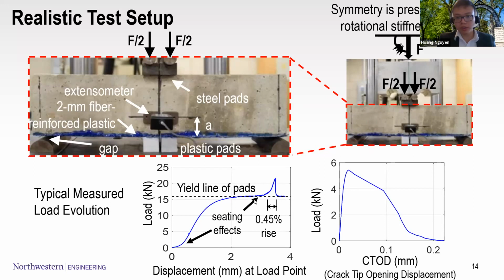And when I did the experiment, I put an extensometer because this is the most exact way to measure the deformation on the experiment rather than the machine displacement, which can cause a mismatch because the machine has some stiffness, right? And extracting that information from the specimen here, you can read the load and crack tip opening displacement and gain some understanding about how the fracture developed and the fracture energy within this material.